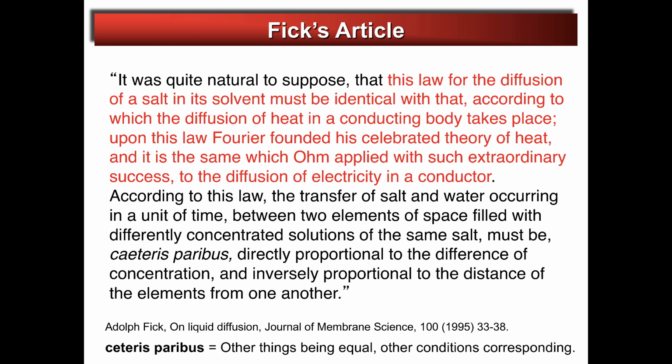And he went on then to formulate what we would now know as Fick's first and second law. And he says, accordingly, the transfer of salt and water occurring per unit time between two elements of space filled with differently concentrated solutions must be directly proportional to the difference in concentration and inversely proportional to the distance of the elements from one another.